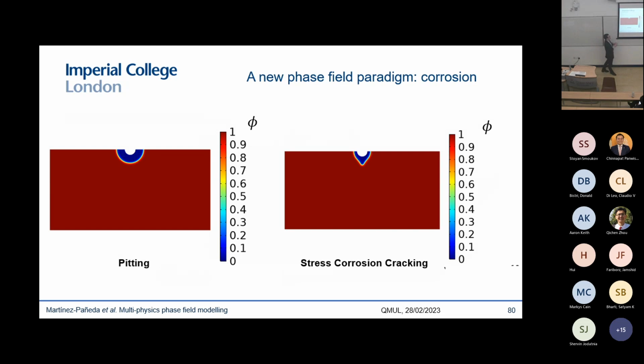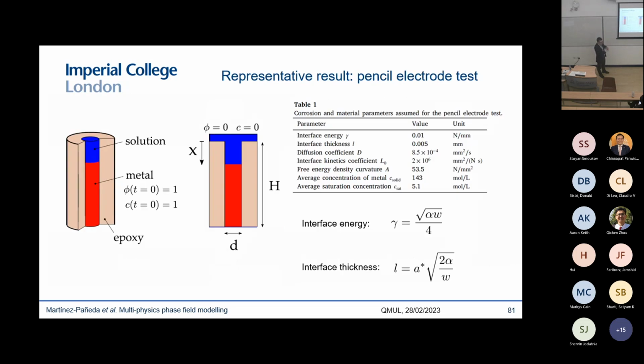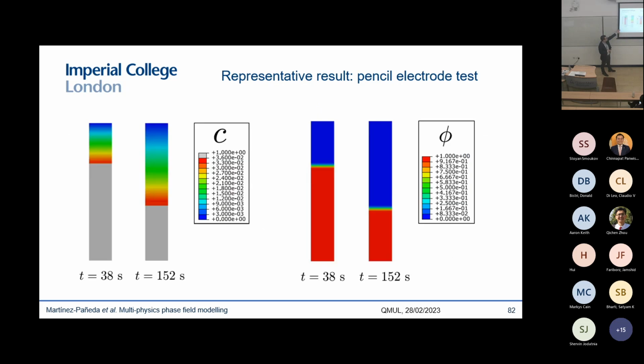And just to show you some representative examples, you can see that we can predict pitting and also stress corrosion cracking very nicely with this method. And we've looked into a number of representative case studies. This is a classic benchmark where you have basically 1D corrosion. And here there's an analytical solution for the case of diffusion-controlled corrosion. And this is basically the kind of results that you expect.